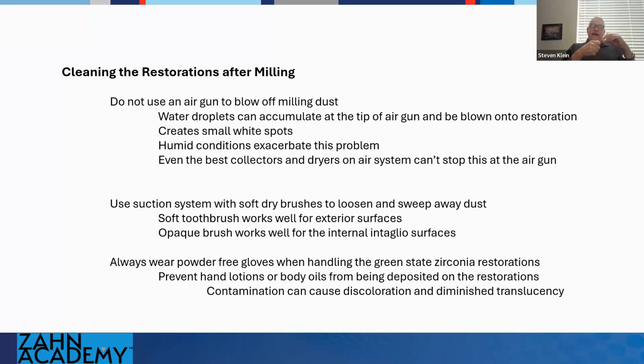So what is happening up at the tip of the air gun is you're getting condensation building at the tip of the air gun, and little water droplets can then be blown directly onto the zirconia. It locks whatever dust was there right onto that surface, and that's it. You're going to have a spot and discoloration right there on that spot, no matter what you do in the sintering process. So I really do not recommend air guns.